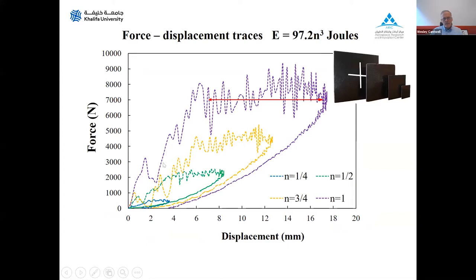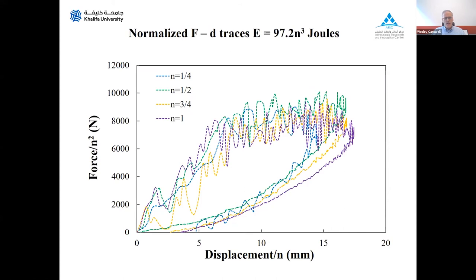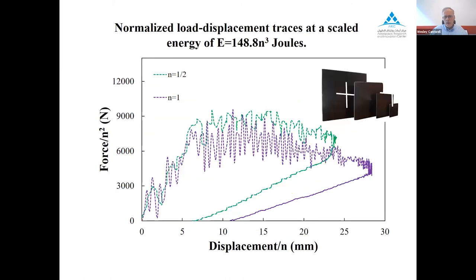We load it up, we get some sort of oscillatory response here. Then we get this type of response here. Now this is all due to fiber fracture, the fibers in the laminate being fractured. And I've just drawn some lines on that to say that we get fiber fractures across the warp and weft directions. So all of this region here is due to fiber fracture. Now that's quite important, you'll see in a minute. But if we just look at the scale force displacement traces, at first view, it looks pretty encouraging. They seem to fall reasonably coherently one on top of the other.